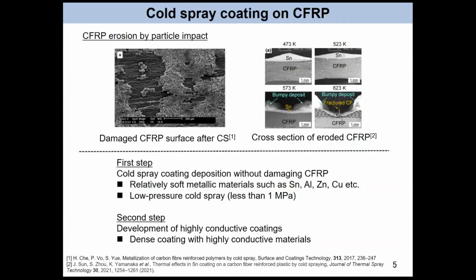But normally, when applying this method to CFRP coating, one problem is CFRP erosion by particle impact, because in cold spray the particles impact at high speed and experience severe deformation. So it often causes damage to the CFRP. This figure shows particle impact causing erosion of the carbon fiber, and also the thermal effect. The name is cold, but actually it is not cold. Hot gas, about 300 degrees, is exposed to the surface. So the thermal effect also causes CFRP erosion.